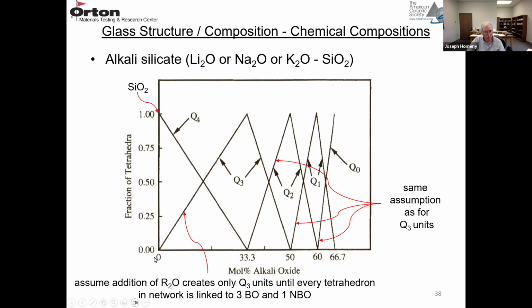This is 0% mole oxide. That would be 100% tetrahedra present. That would be pure SiO2. So here's Q4, and it decreases as you add mole percent alkali oxide. And then as that decreases, the Q3 content increases. So we assume the addition of each R2O unit creates only Q3 units until every tetrahedron in the network is linked to 3 bridging oxygens and 1 non-bridging oxygen.